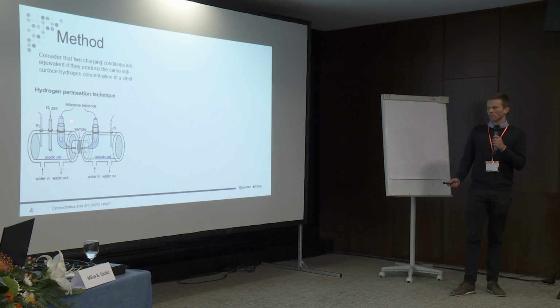The basic is that you have one charging cell and one detection cell separated by your sample. In the charging cell, you can have either hydrogen gas or electrochemical, shown here. So here you would impose a cathodic potential or current density so that you evolve hydrogen on the surface. It will absorb and diffuse through your sample. And on the detection side, you will apply an anodic potential so that once the hydrogen reaches this surface, it is oxidized, and the oxidation current is a measure of the hydrogen flux through your sample.